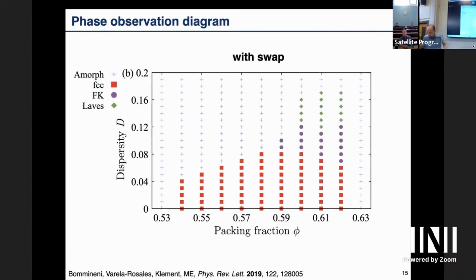So you see essentially what happens is that on this side you now get new types of order. You get here in purple the FK, so these are these Frank-Kasper phases. We didn't attempt in this work to really say which Frank-Kasper phase it is. We see that they're all coordinated 12, 14, 15, 16. Some of those simulations seem to be very complicated, and there might be several Frank-Kasper phases that you can't really split up. And then we see at very high polydispersity, above 12%, up to 16%,